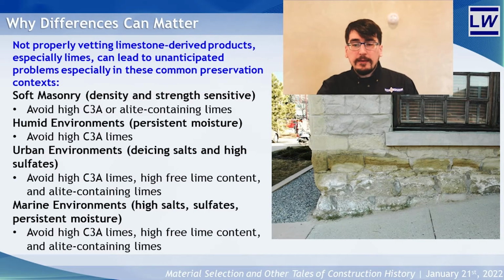Now, on some level, these kinds of minute differences can seem unimportant, or like we academics are splitting hairs. However, in certain environments, they really can matter in a practical way. Indeed, in historic preservation, these kinds of sensitive materials are very common. For example, in soft masonry, such as low-fired or handmade brick, and certain types of soft stone like brownstone, a small difference in density can be the difference between a good water-regulating system that protects the masonry or a water-trapping system that leads to deleterious results. In these places, using a product high in C3A or in alite could literally be the difference between preservation or further deterioration.